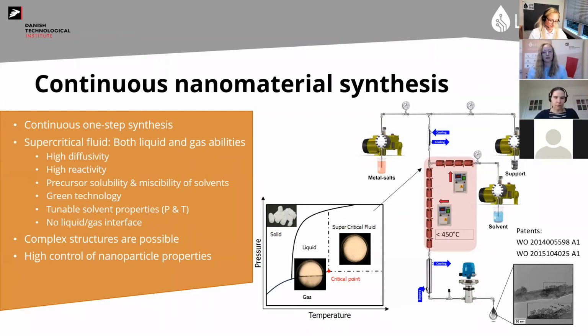They are then pumped into the system and then mixed under room conditions. And then they meet at the second mixing point where the black arrow is. And here we meet a solvent, usually water or ethanol, that has been pressurized and heated a lot, so it moves up to what we're calling the supercritical phase, as you can see in the graph. So if you apply enough pressure and enough temperature, you can go up to the supercritical phase. And what's good about this area is that the solvent then will have the properties of both a gas and a liquid, which means it has high diffusivity and high reactivity.